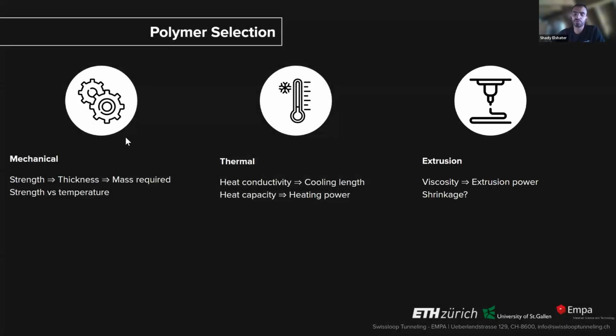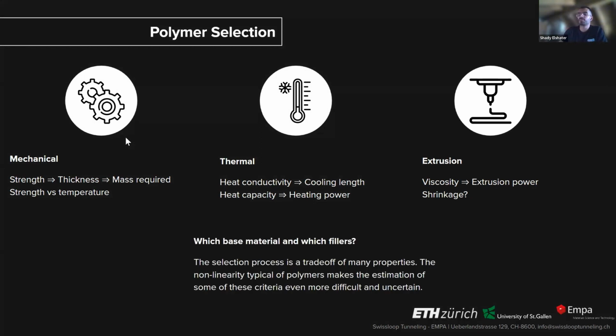And then the extrusion, the last parameter, because the viscosity of the polymer has a big effect on the extrusion power that you need, and then also the shrinkage. That's a very big problem, because if you're extruding and it shrinks, it will basically clamp on the surface and not move anymore. So in the end, it's essentially the selection of the base material and a filler, but there isn't really a perfect polymer.